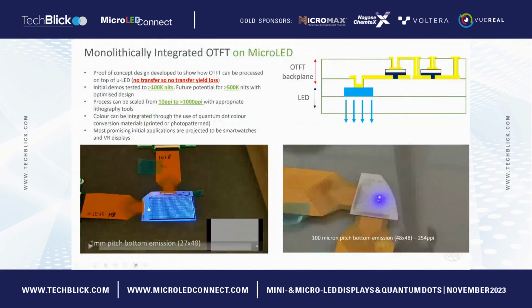So I think you're probably referring to this one. Here you can see in the freeze frame there are a number of missing pixels. This is mainly because this is really a proof of concept that's been done using a contact mask aligner process to pattern the LEDs. When you bring the mask in contact with the sample, it will generate a number of defects each time it touches. So we think that by moving to a more automated projection lithography system for patterning the LEDs, that should clear up a lot of these defects. These were normally bright pixels and we've had to laser these out by breaking them where there's been a defect in the lithography for patterning the LED. So I think these should improve as they get closer towards industrialization.